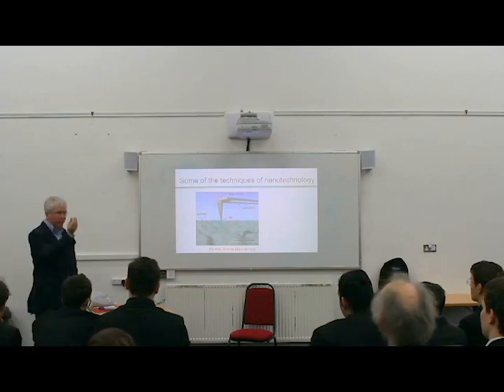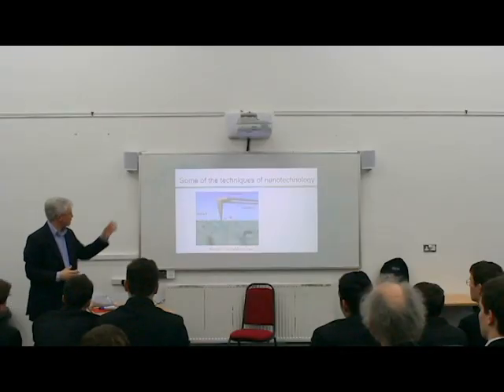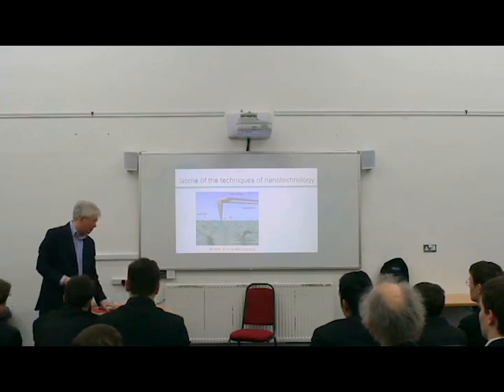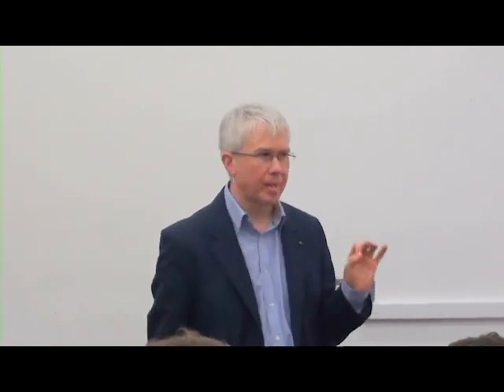What we do is we make a very pointed tip, something that's sharp to within about 10 atoms or so, and we connect it to what's called a cantilever, which is really just a diving board. As that very sharp tip passes over the surface, it goes up and down with the individual atoms as it passes. We bounce a laser beam off the back, and by looking at how the laser beam is deflected, we can actually see the individual atoms. There's a sister technique called scanning tunneling microscopy, which is very similar, but it measures electrical current instead. With a combination of those two, you've got a microscope where you can see things atom by atom. That's pretty amazing.